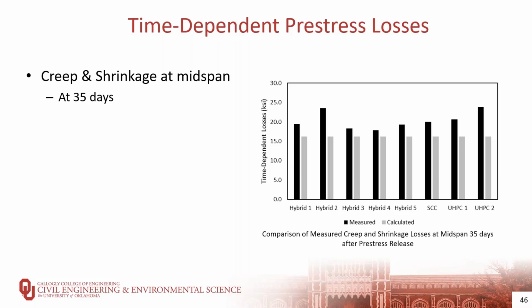Moving on to talk about time-dependent losses. The figure on the right shows the measured and calculated time-dependent losses at 35 days after pre-stress release at midspan. The measured pre-stress losses all exceeded the calculated value obtained from the AASHTO refined method. The measured pre-stress losses of the hybrid girders at midspan were similar to the SCC girder losses.